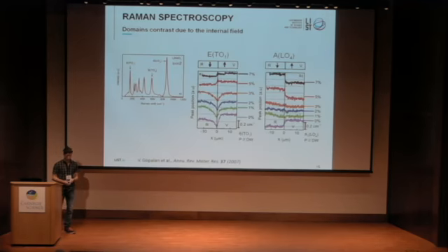And what we get is the following. I just show it for the ETO1 mode, for example, to start. I go from a reversed domain, where I reversed the polarization by applying an electric field at room temperature, across the domain wall, and then to the virgin state of my sample. What you see, first, is that at the domain wall, something is happening. You have a change of frequency at the domain wall.